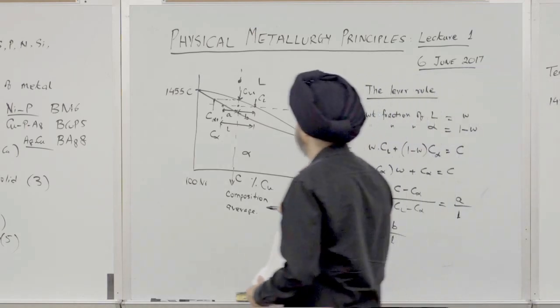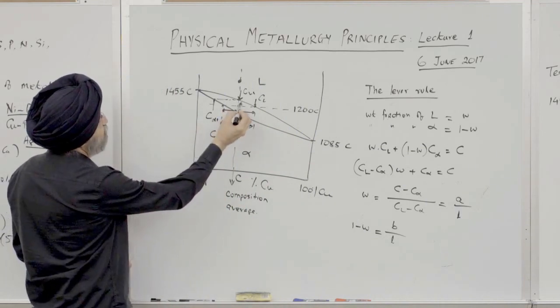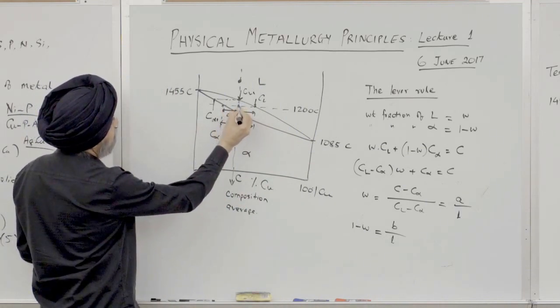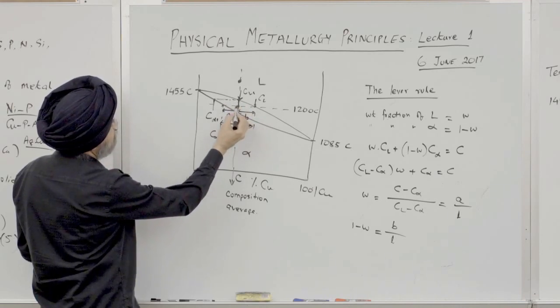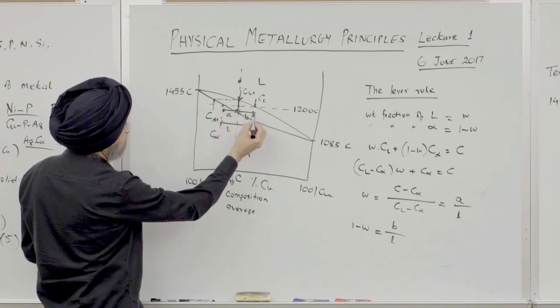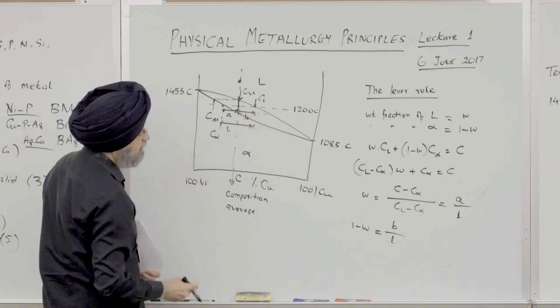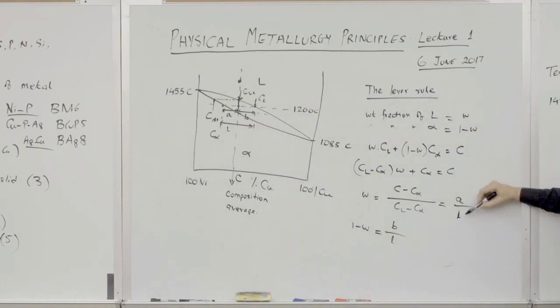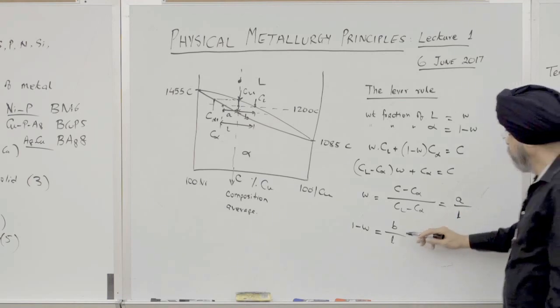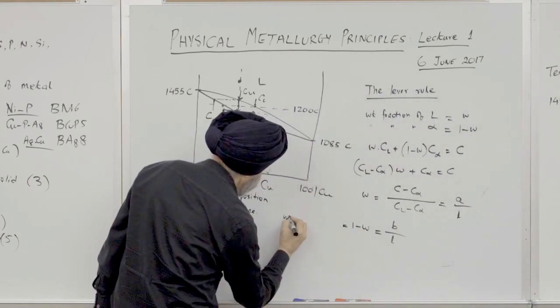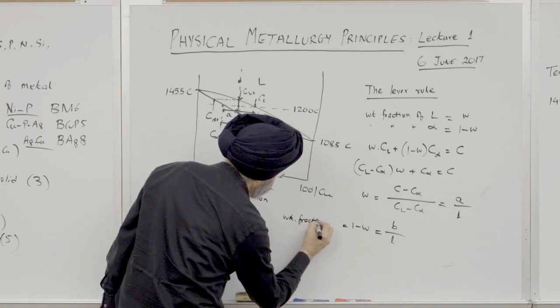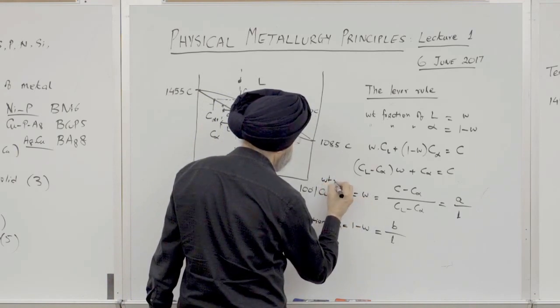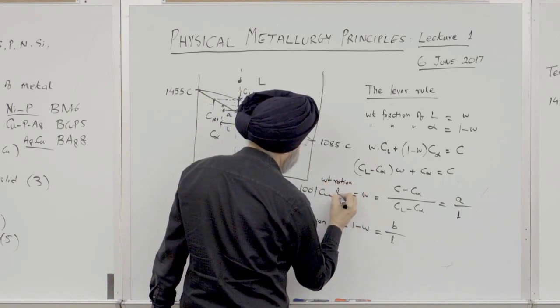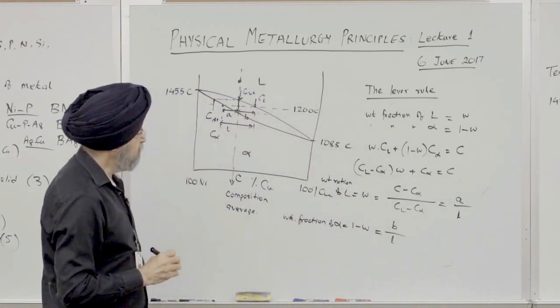So at any point on this phase diagram within this region, as you're coming down from here to there, the amount of solid is increasing, the amount of liquid is decreasing. So you can tell what fraction of the material is liquid by taking A dividing by L, and the amount of solid is B over L. So this is the weight fraction of alpha, and this is the weight fraction of liquid. So that's the lever rule.